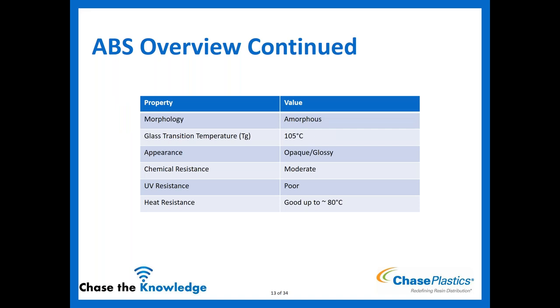I've put together slides with a performance grouping for each material. For ABS: morphology is amorphous, with a glass transition temperature of 105°C. Glass transition is a huge thermal point — for amorphous materials, once you go past the Tg you're past its usefulness range and will lose all properties. So 105°C is somewhat of a limiting factor for the environmental heat the material can see.